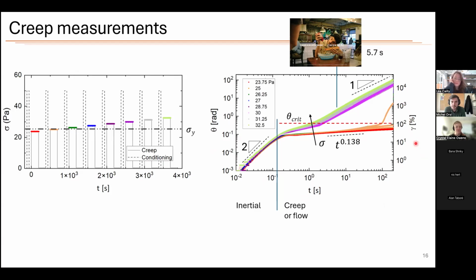And now if we measure in the middle, this is where the most interesting things happen. And so here we see we very neatly complete the data between the low and the high cases. So the most interesting thing here is this is called delayed yielding, where material seems like it's relatively stopped, and then all of a sudden it reaches this critical value and then it flows.